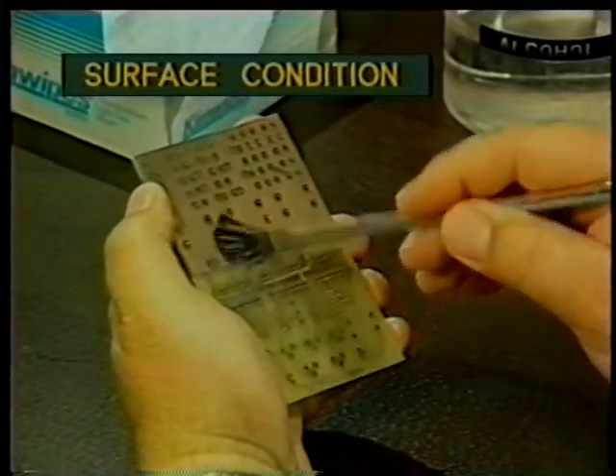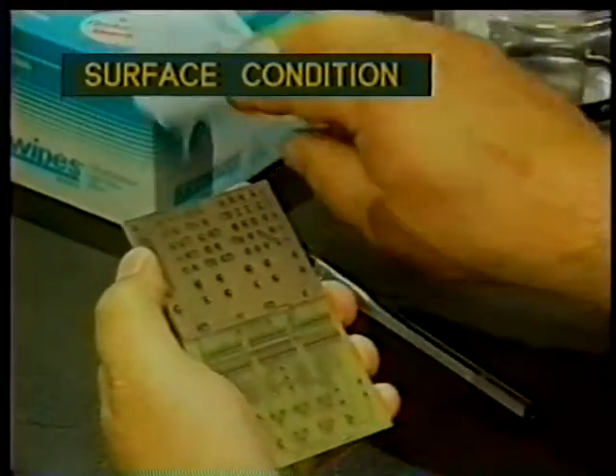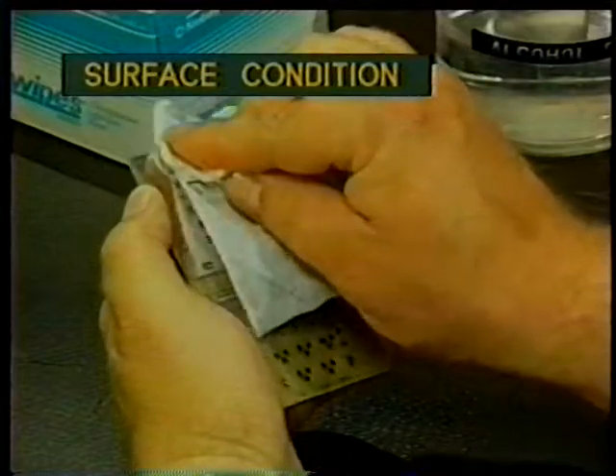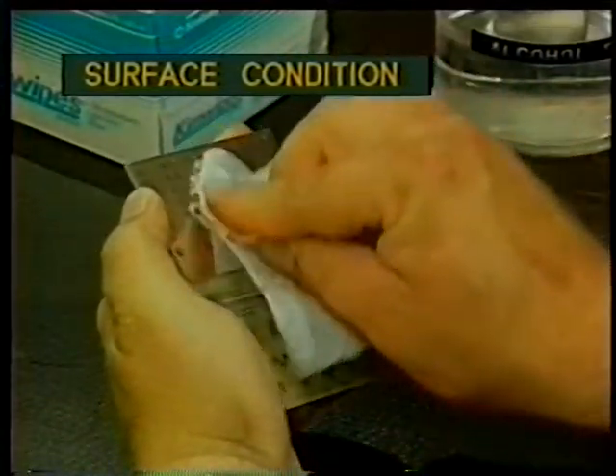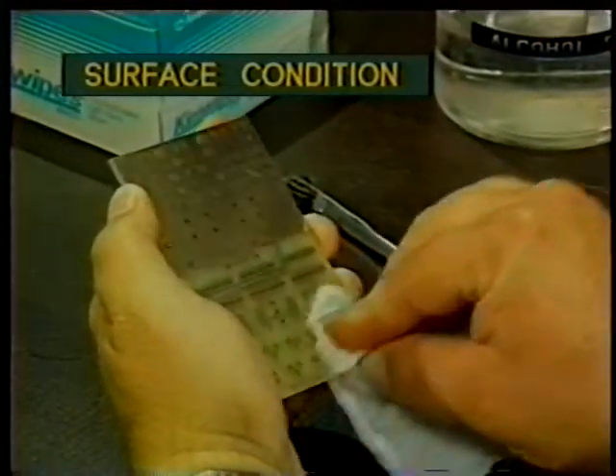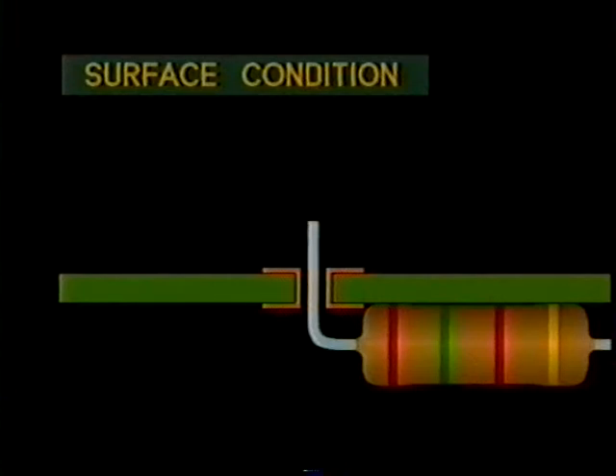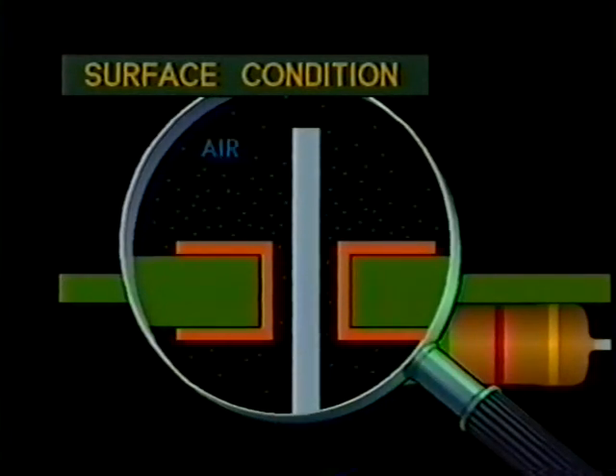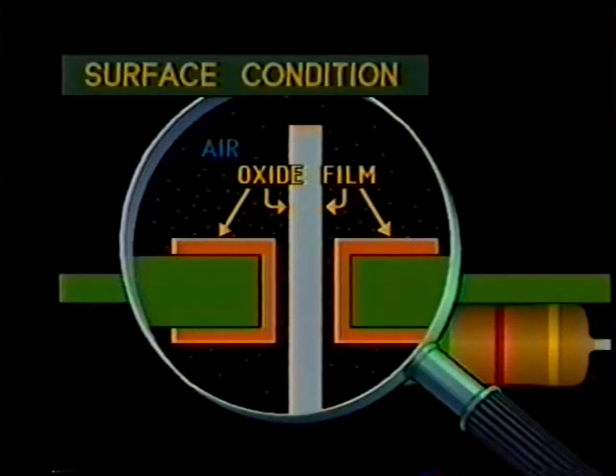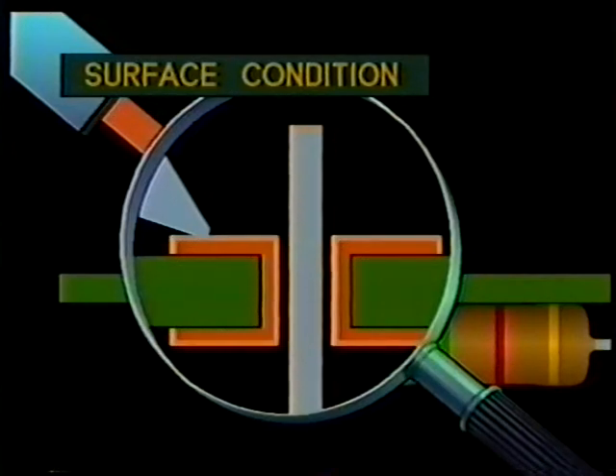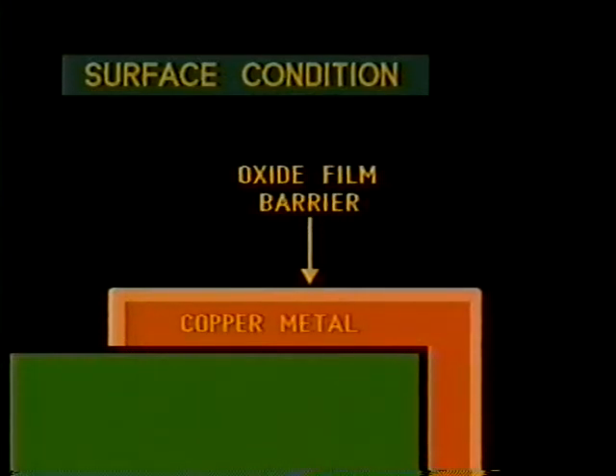Before attempting to solder any joint, the work should always be wiped clean with a solvent such as isopropyl alcohol to remove grease and oil from the surface. While the cleaning of the metal surfaces with solvent is essential to a reliable solder joint, a solvent alone will not do the complete job because when a metal is exposed to air, an oxide film forms on that surface. When metal is heated, as in soldering, the oxide film thickens extremely rapidly, thus creating a barrier which prevents the solder from coming into contact with the metal surface. The solder acts like water on an oily surface. No wetting action takes place, and the solder can be easily scraped off. For a good solder bond, surface oxides must be removed during the soldering process.